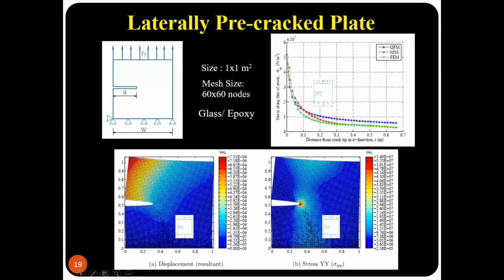Now, once we verified our model, then we applied different simulations in composite materials. So initially, we considered that laterally pre-cracked plate, wherein we can see here, this is the pre-cracked plate with initial crack, initial horizontal crack on the left side as shown here of the size A. And when we perform the simulations for given loading conditions,